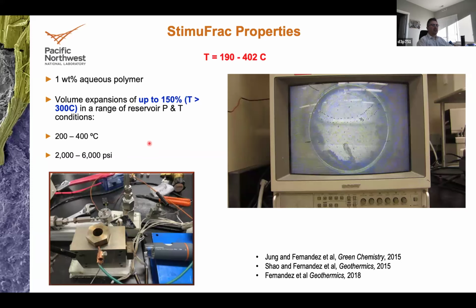So initially what we thought is that, well, we can use this polymer solution in the presence of CO2 that expands in volume as a way to increase stress in a confined environment. Later, you will see that this is highly dependent on temperature, and viscosity also plays a role. And another property that the fluid has, since this is a polymer solution, it's a surfactant like soap in water, is the reduction in surface tension. So that reduction in surface tension together with the CO2, which has negligible, zero surface tension, it can make good things in terms of penetration in the wellbore.